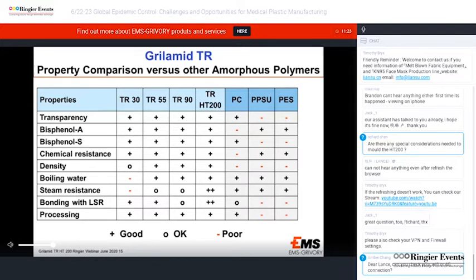Density: here, Grilamid TR shows a clear advantage, as seen in previous slides. For the boiling water resistance, Grilamid TR, except TR30, shows comparable results to the other products. For steam sterilization at 134 degrees, generally Grilamid TR shows a poor resistance. However, with our TR HT 200, we have developed a clear polyamide which has superior resistance when compared against polycarbonate and sulfones.